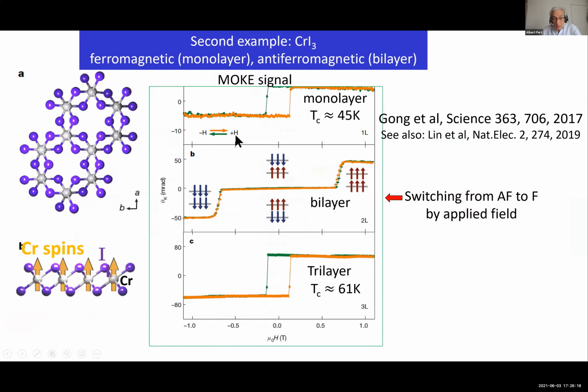And in fact, the classical property that has been investigated by many groups is that for a single layer, the system is ferromagnetic, with a very low ordering temperature, of course, 45 Kelvin. But for a bilayer, now the system becomes antiferromagnetic, with antiferromagnetic ordering of the two layers. And of course, this antiferromagnetic system can be switched to ferromagnetism by applying a magnetic field, as it occurs even in 3D antiferromagnetic compounds. And then again, for a trilayer, it becomes ferromagnetic again.